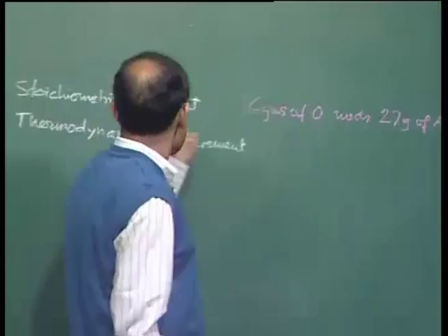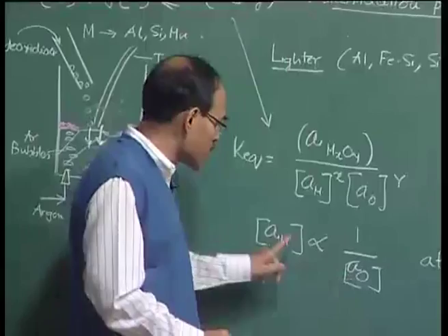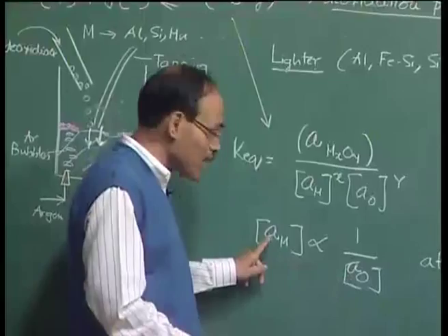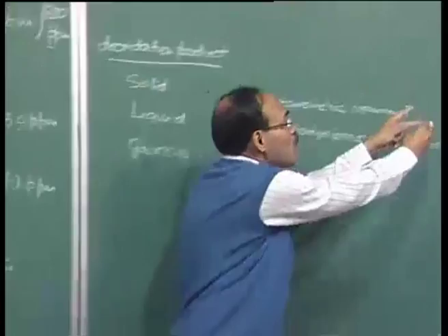Beyond this stoichiometric requirement, we have another requirement to fulfill, and that is the thermodynamic requirement, because I mentioned to you that for a given level of final oxygen, there is going to be some equilibrium aluminium content in the bath itself. So, we have to find out that, well, one part of aluminium has reacted with oxygen and has gone into the slag phase.